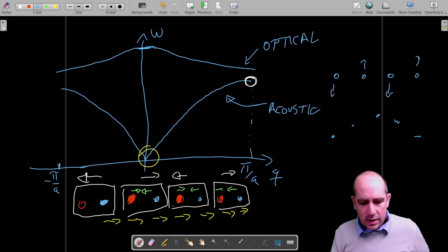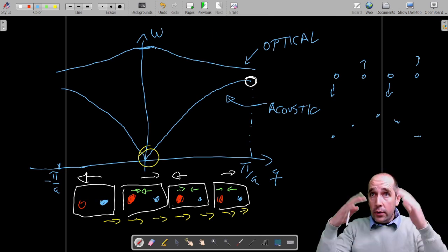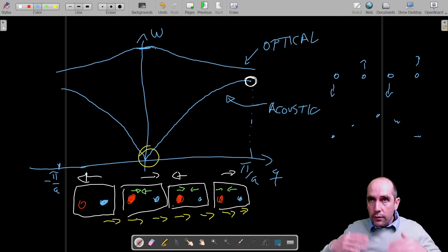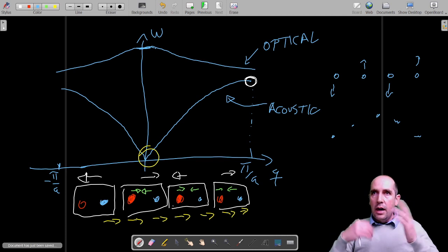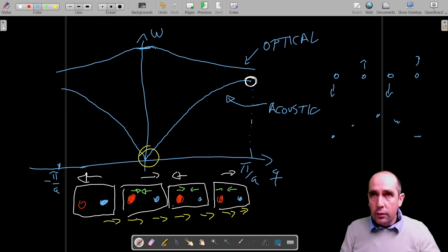And essentially, these transverse phonons also exist, and we can do the math. It's not very different to what we already saw. And what we obtain is that, again, when you have two types of atoms, you can have two branches, which are the transverse-acoustic and transverse-optical phonon. So in the end, we have more or less four branches, four phonon bands, if you want to call them like that, which correspond to